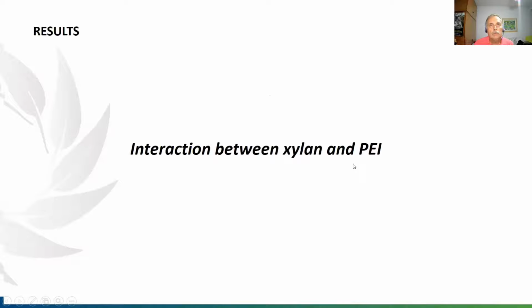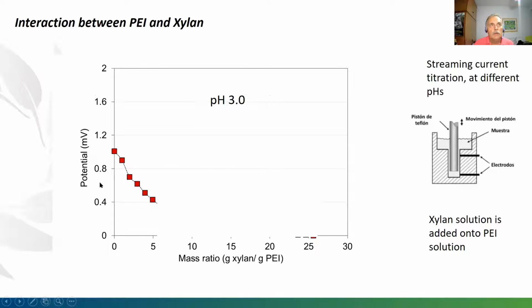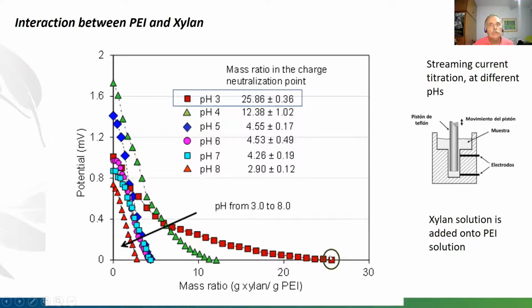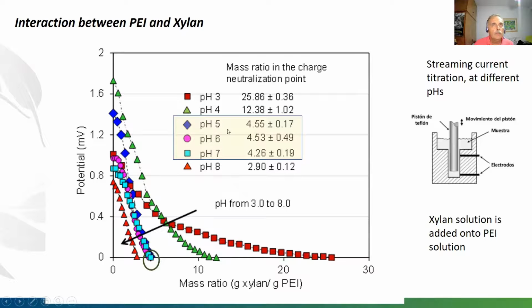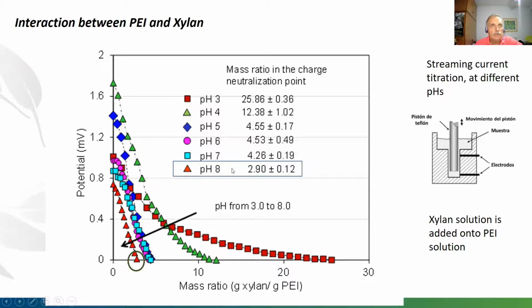First, we consider the interaction between xylan and PEI. We see here the streaming potential that is reduced when we add xylan to the PEI solution. And we found here the mass ratio that corresponds to the neutral condition. For different pH, this neutral mass ratio is reduced. For pH 4 and for pH 5, 6, and 7, the neutral mass ratio was similar, and it's a bit lower for pH 8.